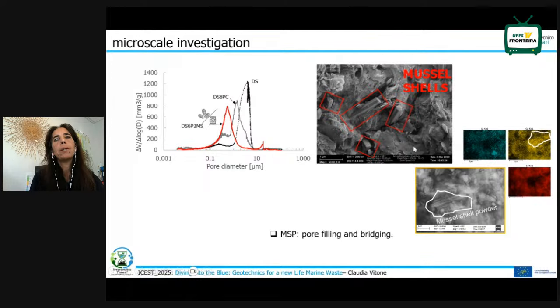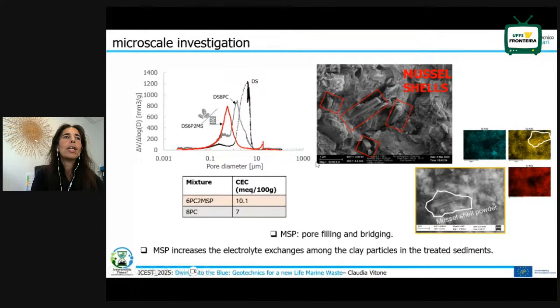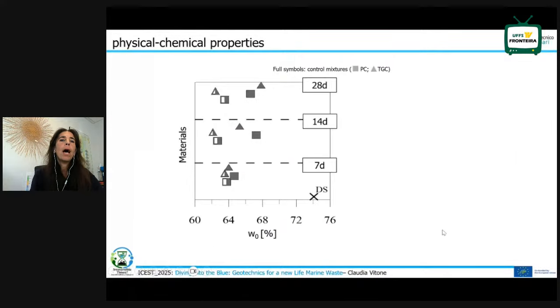Also from the SEM imaging, you can see here the mussel shells, as also confirmed by the elemental analysis. So essentially, here we can suspect that the mussel shell powder is pore filling and is also bridging the clay particles in some way. But the mixture with shells is also characterized by higher cation exchange capacity, compared with the control one. So essentially, it seems that mussel shell powder is increasing the electrolyte exchanges among the clay particles in the treated sediments.